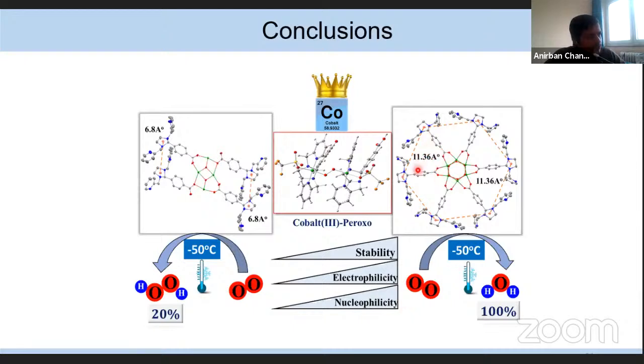When we have more constraint, for the hexanuclear complex the distance between the ligands is 11 angstrom, whereas in the tetranuclear complex the distance is around 7 angstrom. So the peroxo species formed from the hexanuclear complex suffers from more constraint, and also because all these centers are equidistant, maybe there is a more synergistic interaction or cooperative effect operating, which is the key for its better electrophilic character.